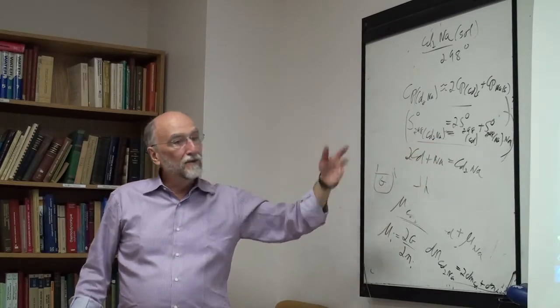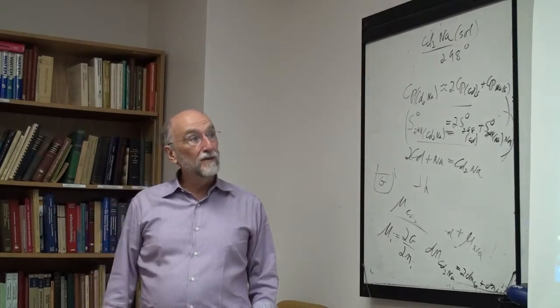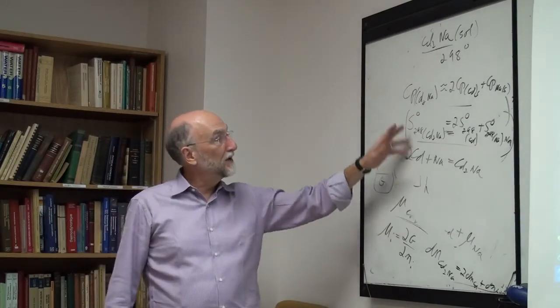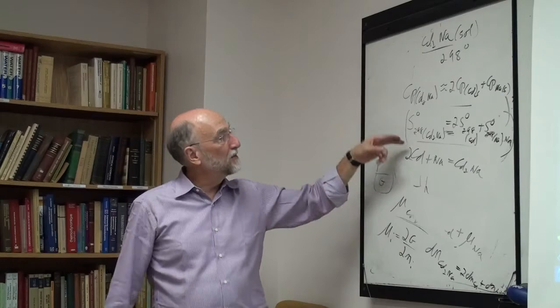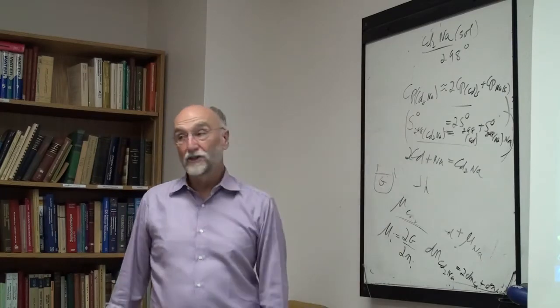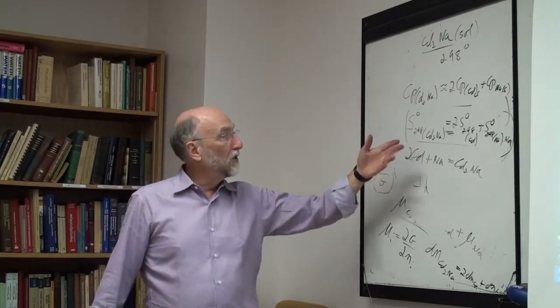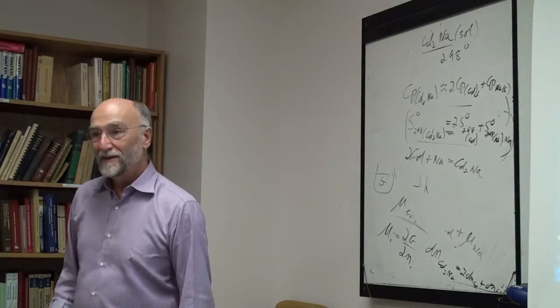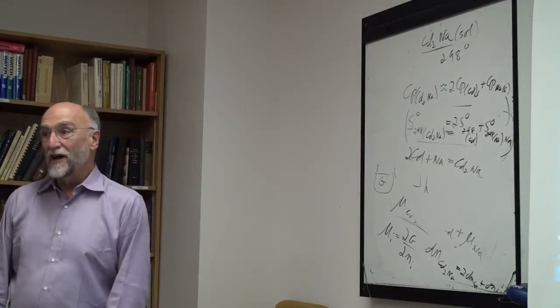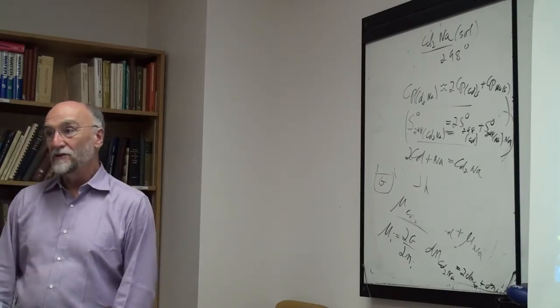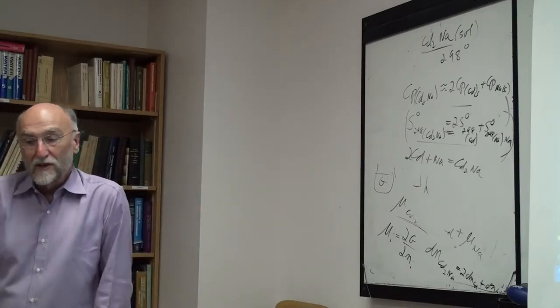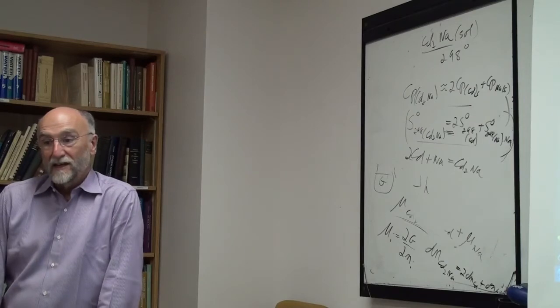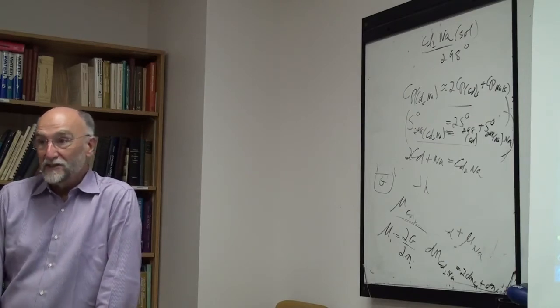But if you're going up to something like 30, 40, you see this oftentimes in the literature too. This is fitted up, the heat of formation was known, and the optimization gave you an entropy of formation at 298 per mole of metal of 70 joules or something. It's wrong. The entropy change is just not that big. You don't mix two solids to get another solid and get 70 joules. Remember, 70 joules per mole, that's like an entropy of vaporization.